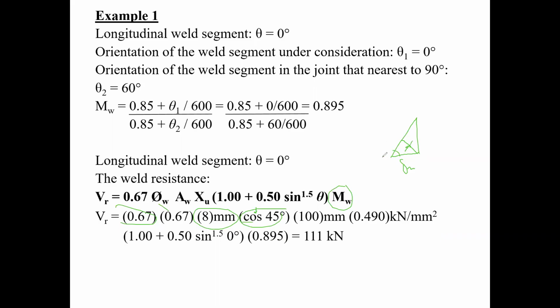It gives me the length of the throat here. That's why I put 45 degrees. You could use the sine of 45. The sine of 45 and the cosine of 45 are both 0.707, exactly the same value. L is the length, so this gives me the Aw value here. Now, this is the strength of the electrode, 490 megapascals, which is 0.49 kilonewtons per millimeter squared. In other words, I have 490 newtons per millimeter squared, and to convert to kilonewtons I put 0.49 kilonewtons per millimeter squared, and that gives me the value of the electrode, Xu.